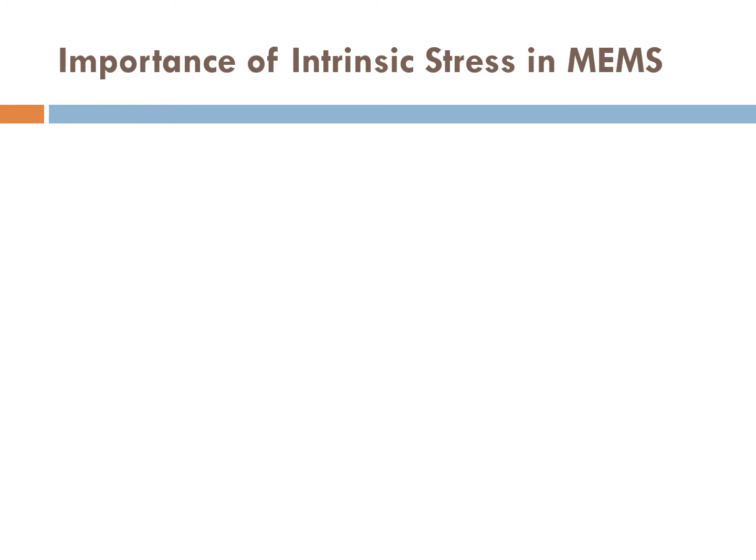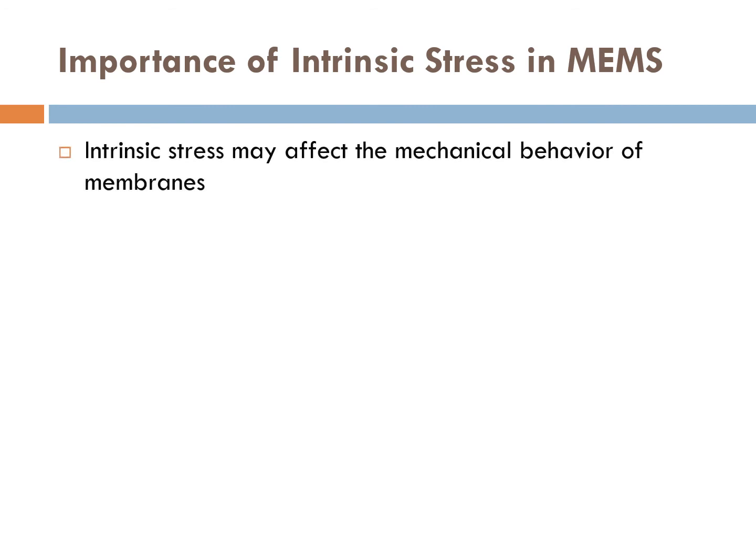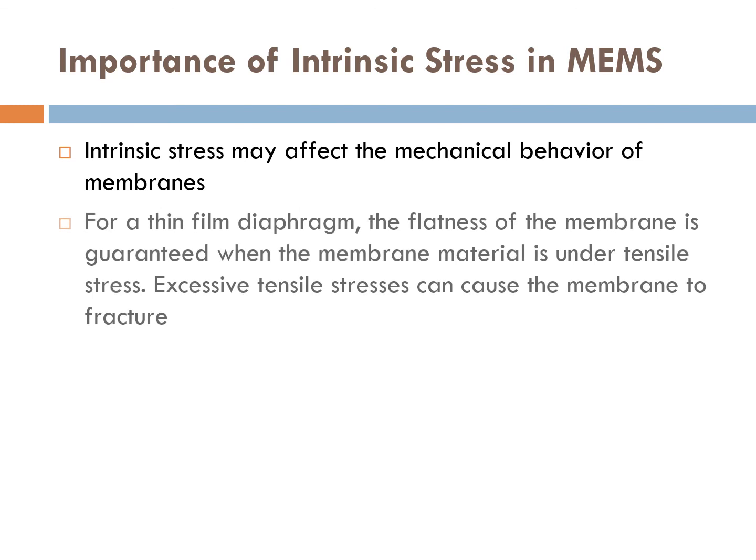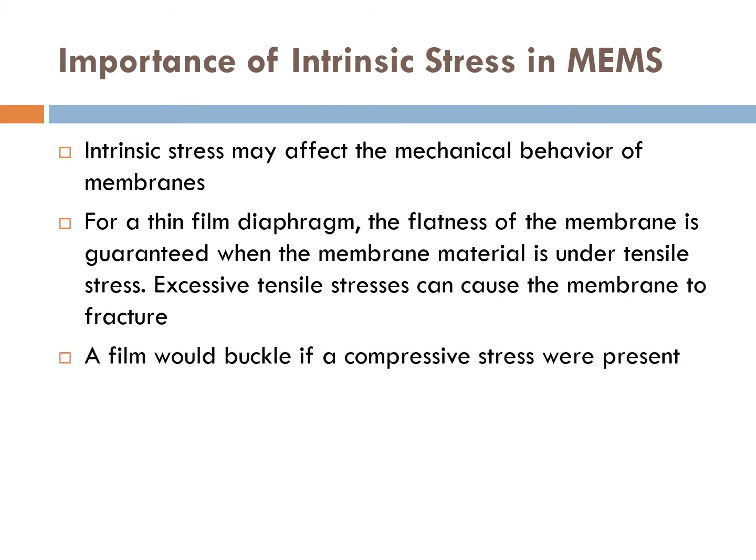Intrinsic stress may affect the mechanical behavior of membranes as well. For a thin film diaphragm, the flatness of the membrane is guaranteed when the membrane material is under tensile stress. But excessive tensile stress in a clamped membrane can cause the membrane to fracture. A film, on the other hand, would buckle if the compressive stress were present.